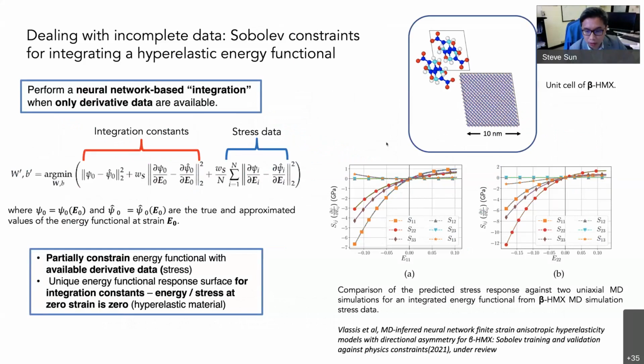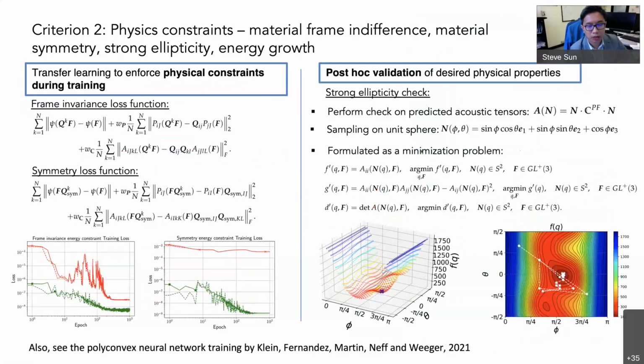This method has not only been applied on direct numerical simulations for the finite element. It has also been applied in our recent work on simulating HMX polycrystal energetic material for finite strain problems. In this case, we don't have the hyperelastic energy data, but we have the stress data, and then we use the initial point of the energy to train the constitutive law for this polycrystal. We can see that even without a very sophisticated multi-layer perceptron, we can create a very good match in the constitutive response on the stress strain curve. But more importantly, we can also introduce the physics through a transfer learning strategy.